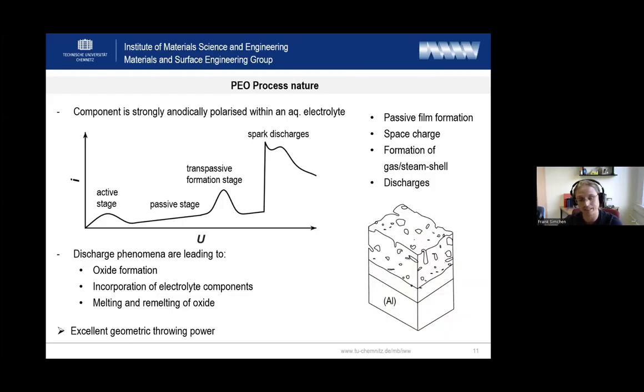So if you think about metal deposition, you apply an electrical conductive coating material on an electrical conductive substrate. So the field lines don't have any reason to go behind undercuts and inside of drillings maybe. So the throwing power is not so perfect. But when you apply a polarization of maybe 500 volts, and in some regions of your components you have electrical isolating oxide, and in other regions you still have naked metal, the discharges have reason to appear there. So you can apply a coating on geometries which are really complicated.